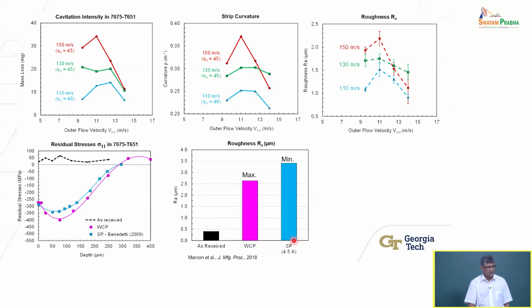That's the traditional process, where the least roughness is worse than the worst case roughness in my case. So that suggests that yes, while you do some roughening, it is not as bad as the other process, right? So that's a promising result, at least.